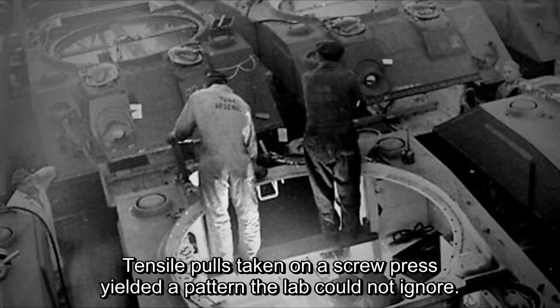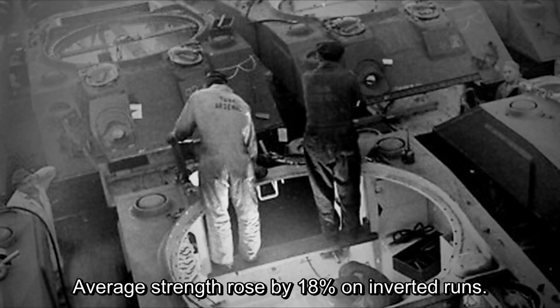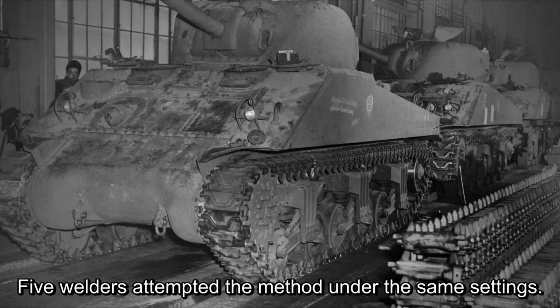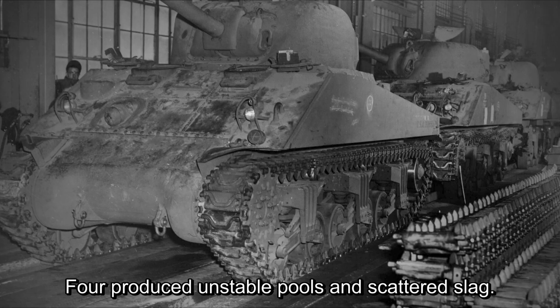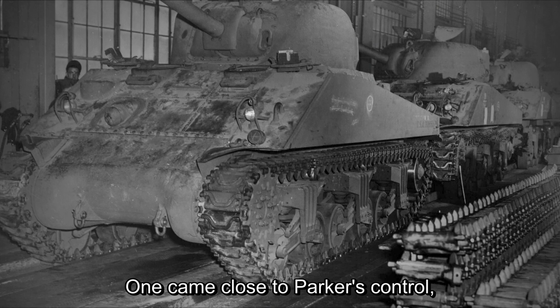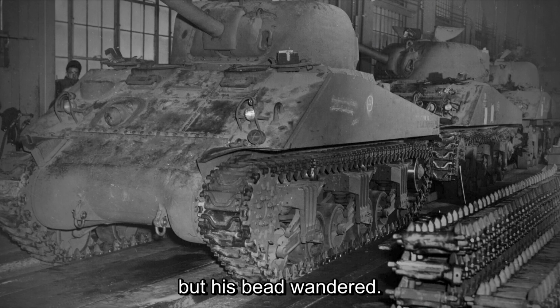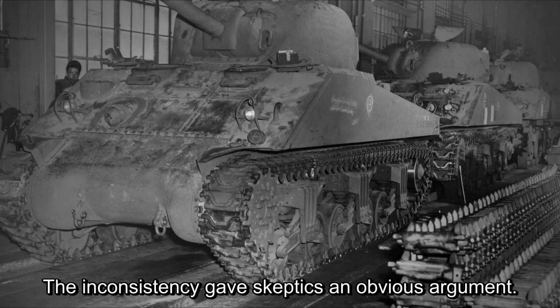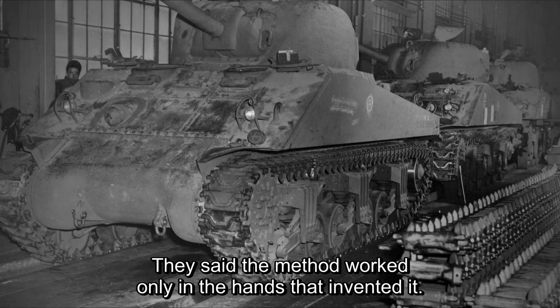Tensile pulls taken on a screw press yielded a pattern the lab could not ignore. Average strength rose by 18% on inverted runs. Replication was the next hurdle. 5 welders attempted the method under the same settings. 4 produced unstable pools and scattered slag. 1 came close to Parker's control, but his bead wandered. The inconsistency gave skeptics an obvious argument. They said the method worked only in the hands that invented it.